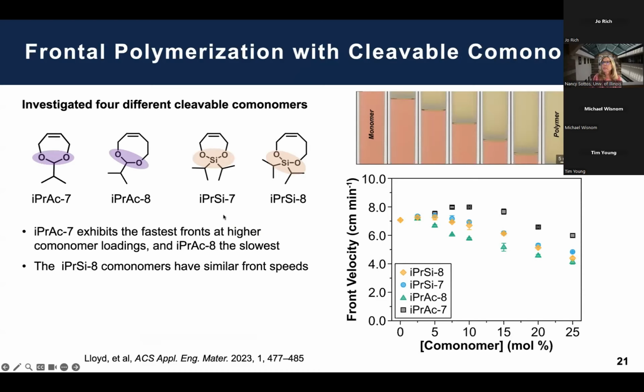I show them here. These are cyclic silyl ethers and cyclic acetals, 7- and 8-member rings. And basically the takeaway is that as we add amounts of comonomer, it actually reduces the ability to frontally polymerize. So we want to add as little as possible. But what the graph on the right shows is that, yes, I can add this comonomer. It still will frontally polymerize. It slows down as you add more, but you really don't want to be adding 20 mole% of the comonomer. I want to stay in this window, as you'll see from the properties.